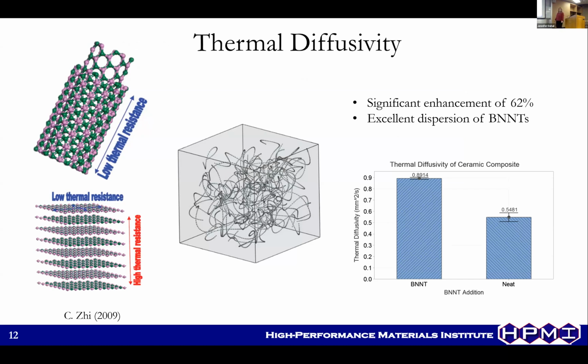All right, so thermal diffusivity, we studied by laser flash analysis. This is, I think, one of the most exciting enhancements. We have a significant enhancement of 62% higher thermal diffusivity with, again, only 0.1% weight BNNT, which has great promise with more high-temperature ceramics like silicon carbide and silicon nitride. That increase is likely due to the manufacturing parameters of paying close attention to good dispersion. We know that with a BNNT, we have low thermal resistance across these planes, which is in the direction of the tube, and high thermal resistance across the different walls of the tubes. So when you have a good dispersion, this will spread the heat more evenly and allow us to capture the properties of the thermal